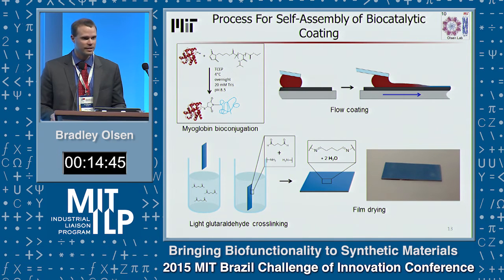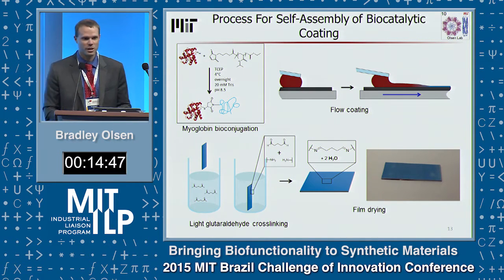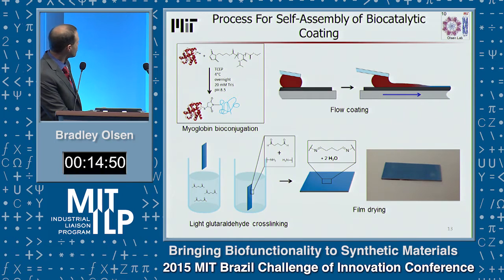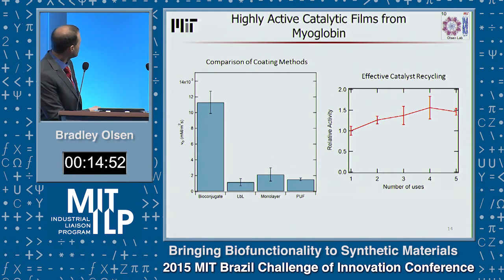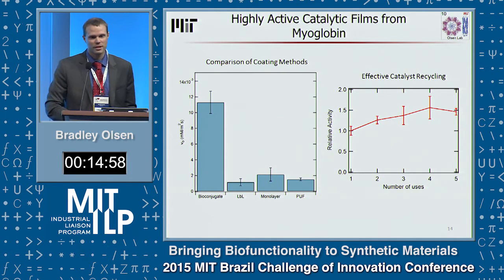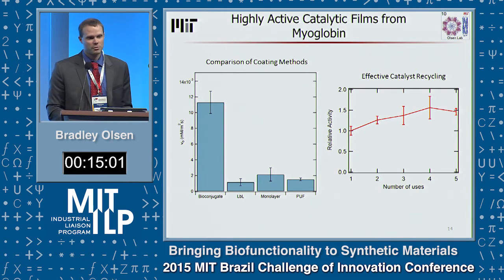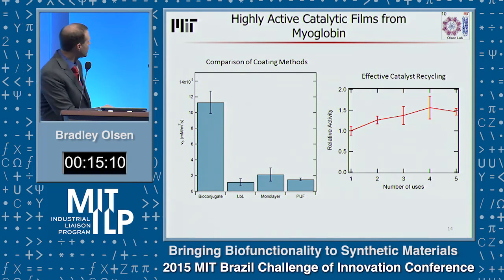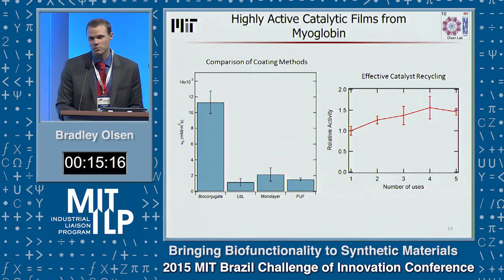It's lasted at least 10 days in continuous operation with no noticeable degradation. And when you compare the catalytic activity per unit protein of this material to other techniques for producing immobilized protein and surface coatings, we get about a 10-fold enhancement in the performance without an attempt to individually optimize any of the techniques. So using each of the techniques essentially as disclosed technology, we get a huge 10-fold enhancement, and we've demonstrated the ability to recycle the catalyst at least 5 times with the model protein.